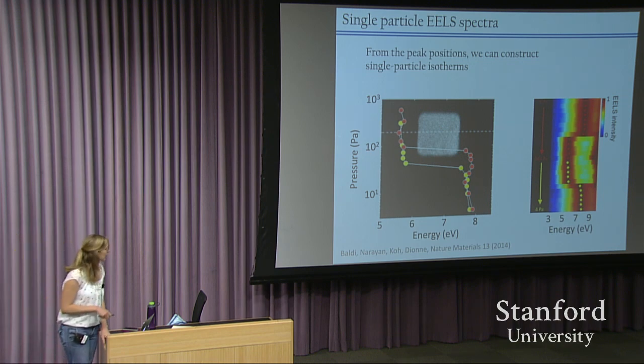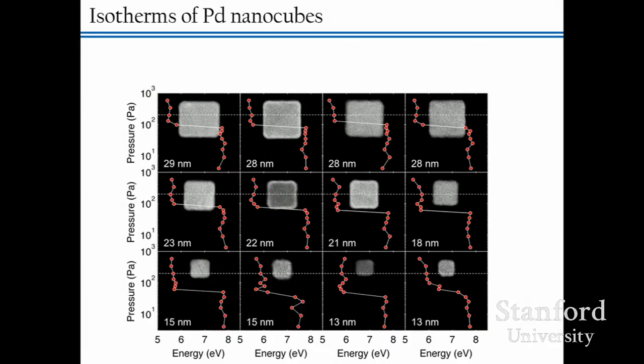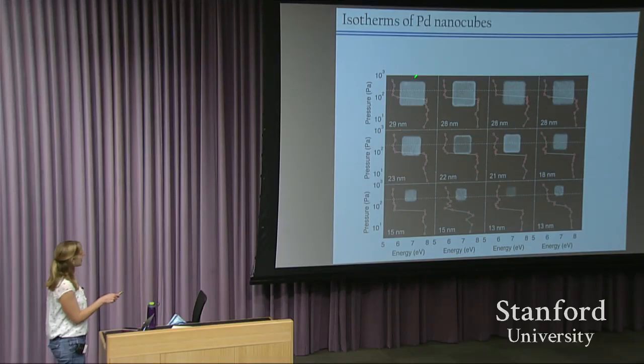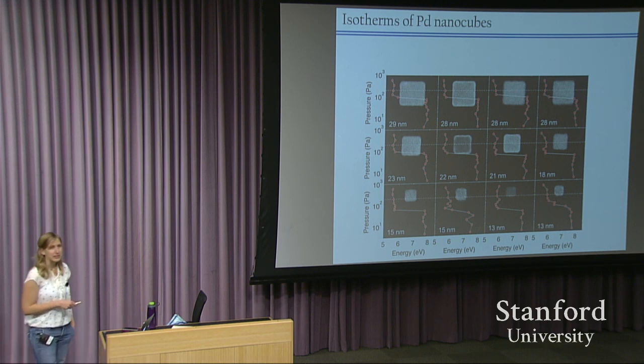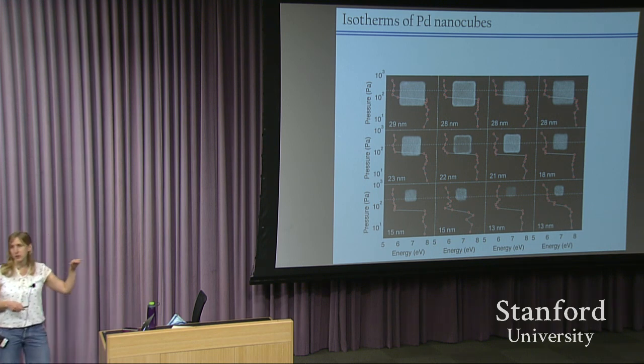So we can do this study on a number of particles. Here we're varying the particle size from about 13 nanometers up to just about 30 nanometers. We've now done these studies up to a few hundred nanometers, but I just want to give you a flavor of what we've seen. First of all, we've noticed that all of these nanoparticles, down to about 15 nanometers in size, exhibit these very sharp transitions from the alpha phase to the beta phase without there being really any coexistence.